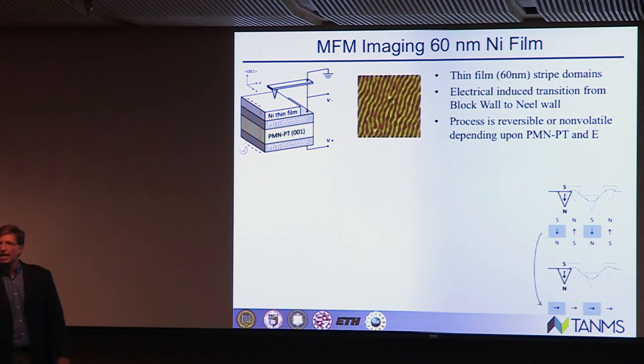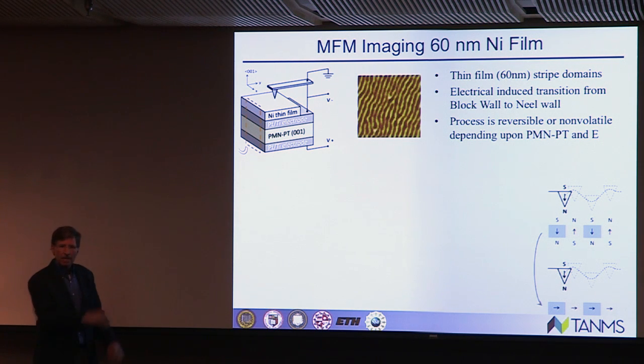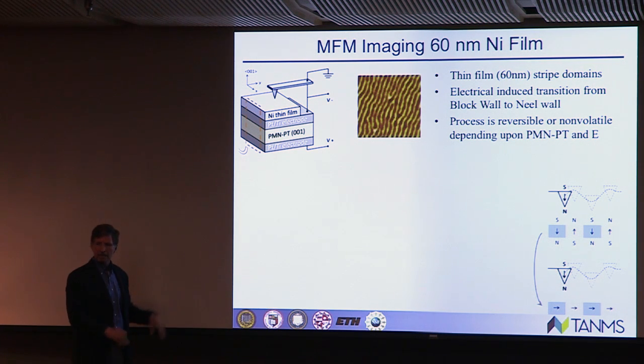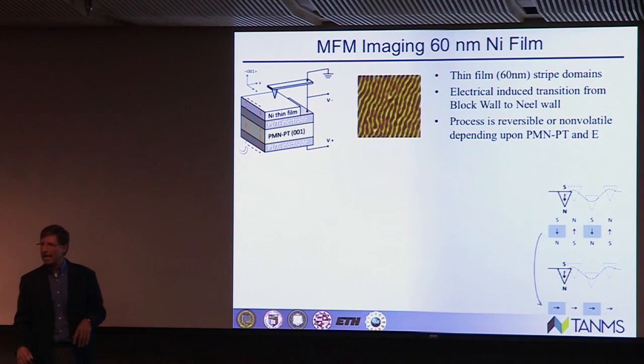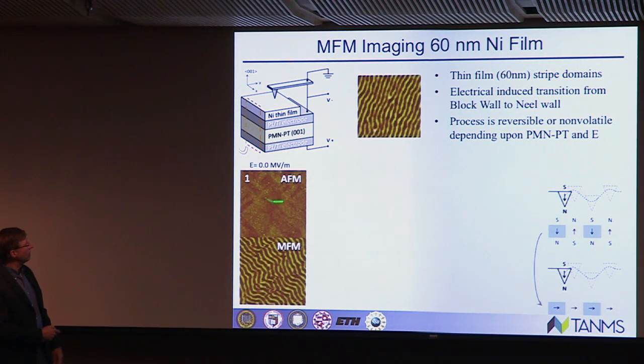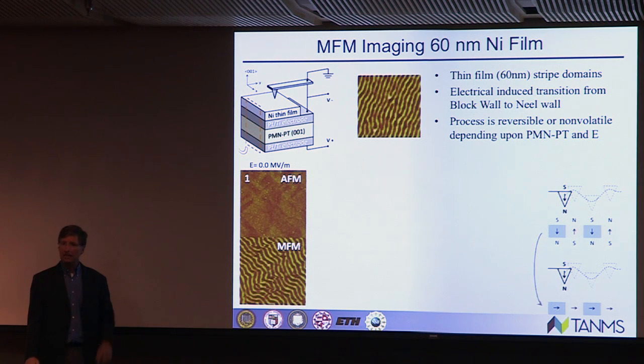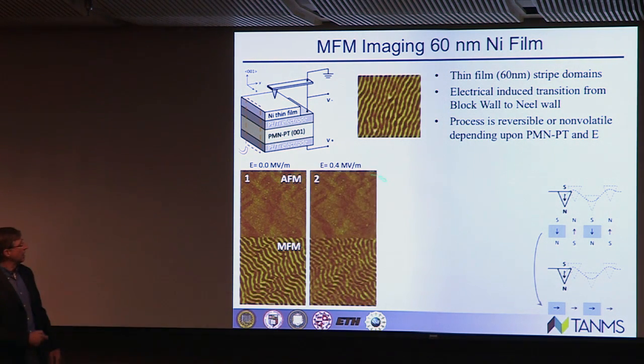Now, by the way, this is an entirely different phenomenon than you saw in the preceding slide. Before, there were no out-of-plane domains. Now they're out-of-plane. Now let's go in and look at what we can do here. So we're going to look at an AFM image first, and down here is the MFM image. And this is at 0 megavolts per meter. Now let's apply a little bit higher electric field. We've applied 0.4 megavolts per meter.